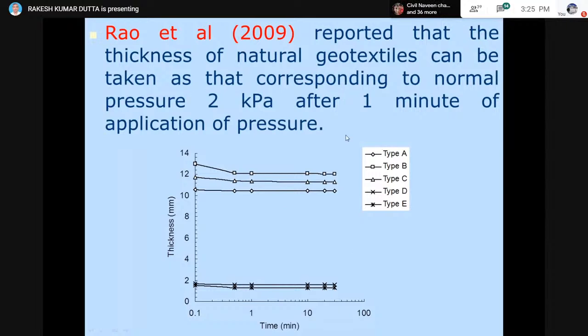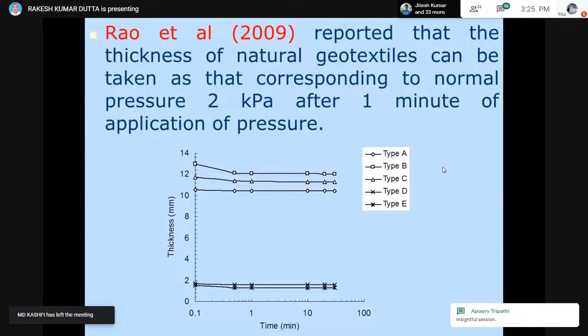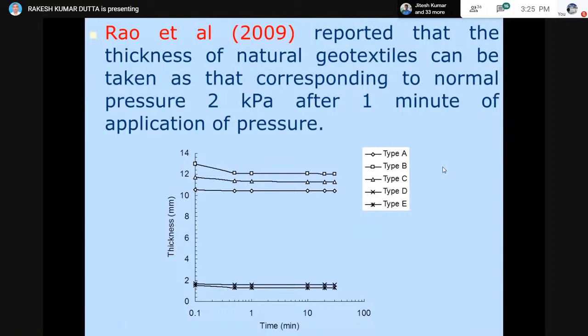So the first conclusion drawn from this study was that if you want to check the thickness of coir geotextiles using the test procedures laid down for polymeric geosynthetic products by the ASTM, you can measure their thickness upon application of a 2 kPa load for a period of 1 minute, and after 1 minute you can take the actual reading for the thickness of that particular material.